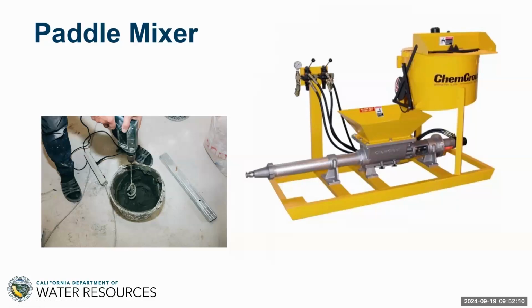One of the beauties of the high-speed mixer is it's very fast. You can assimilate a 3-bag mix in about 2 minutes. That's very quick. And on the right-hand side is a typical, if you like, commercial grade, industrial grade paddle mixer. This one's produced by ChemGrout, who also do high-speed mixers as well. They're based up in Illinois. Very, very fine company. Next slide.